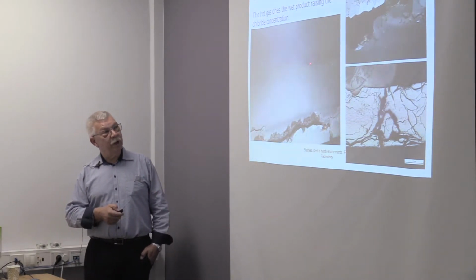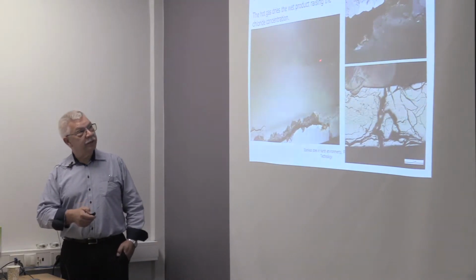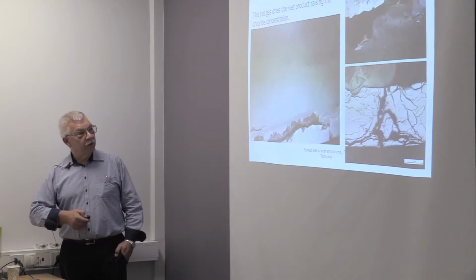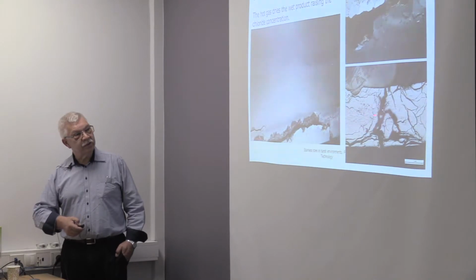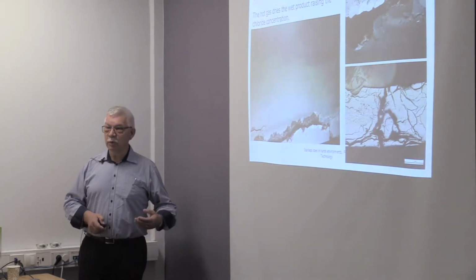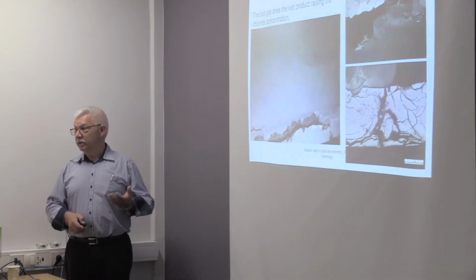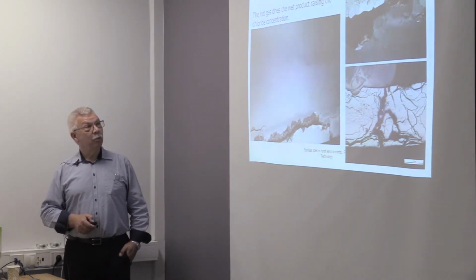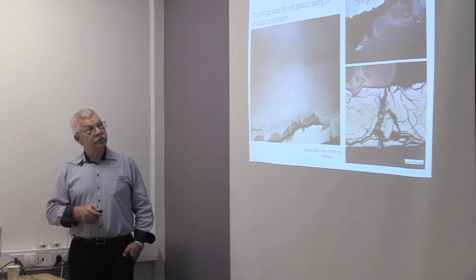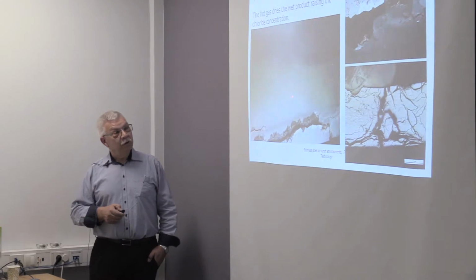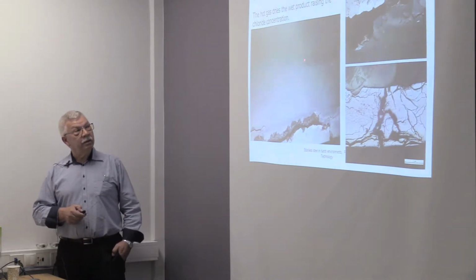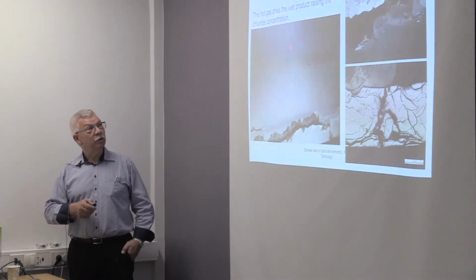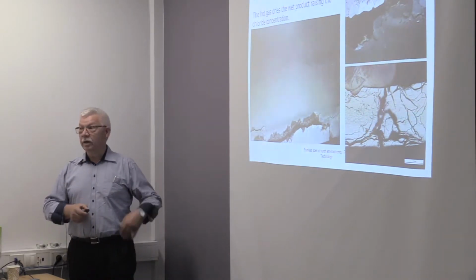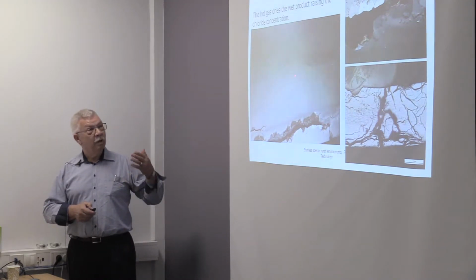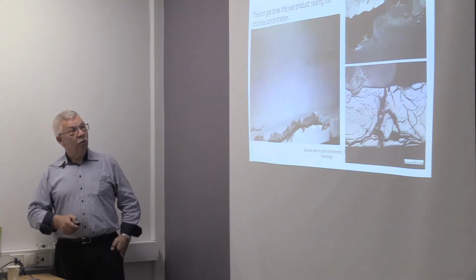Again, there's a relation to welding because of the stresses; there's a weld here which has been polished off. We also have a weld here, and the stresses around these welds, you can see the weld metal like this. The stresses here are the driving force together with the chloride level and the temperature in this chamber. Once the material has dried up, so that it's totally dry, no humidity in the deposit, then in fact there will be no more corrosion. So if we have a weld up here where everything is dry, it's safe. But exactly here where we have the wet product drying up, we get all this cracking.